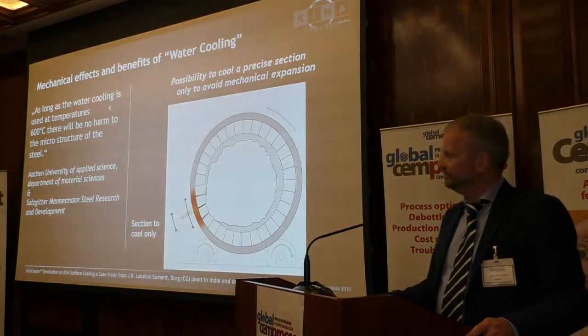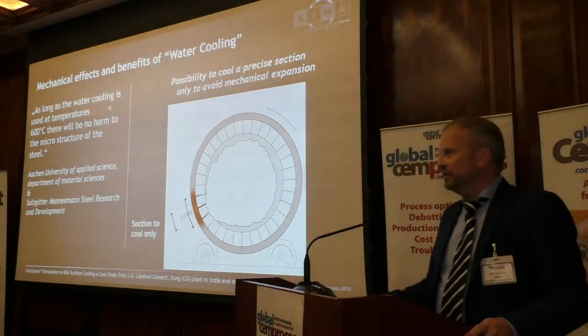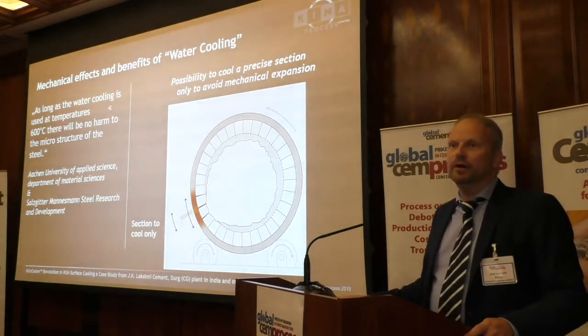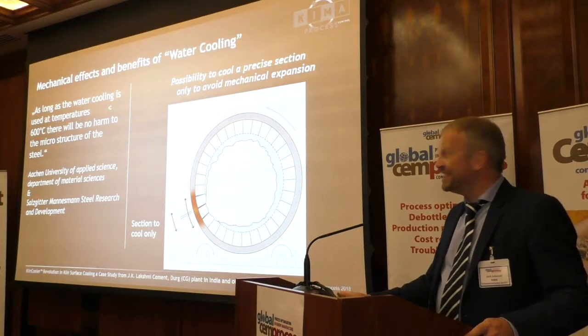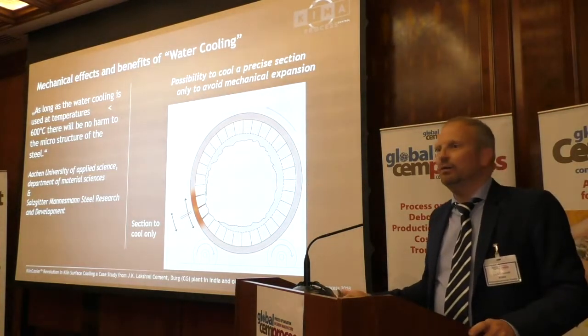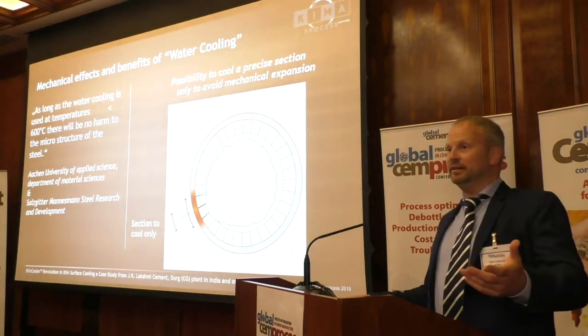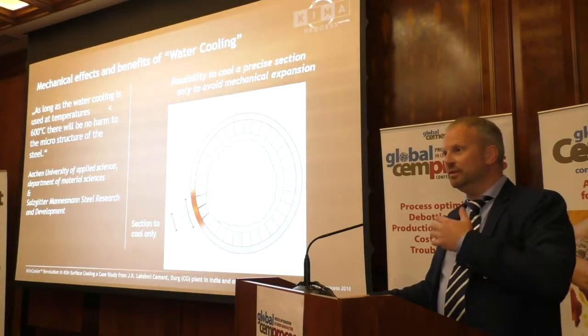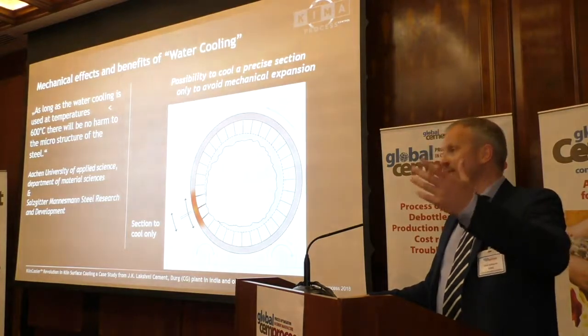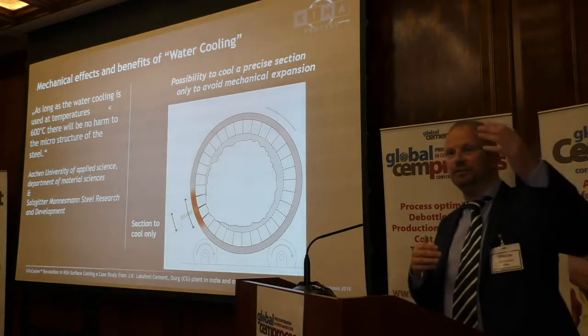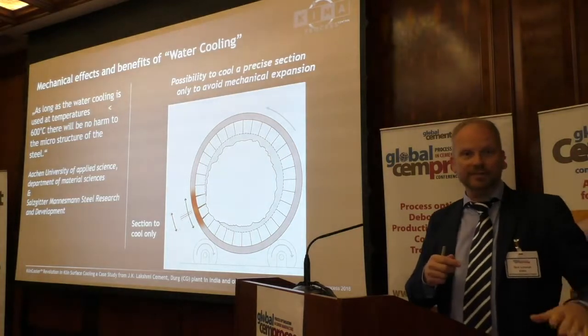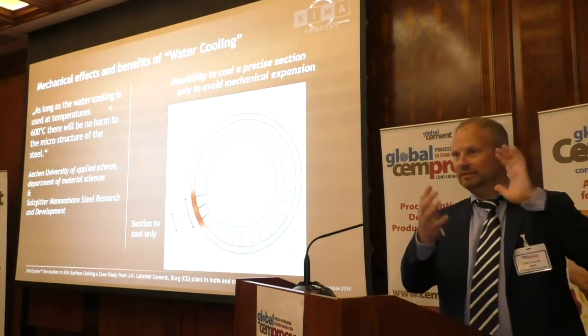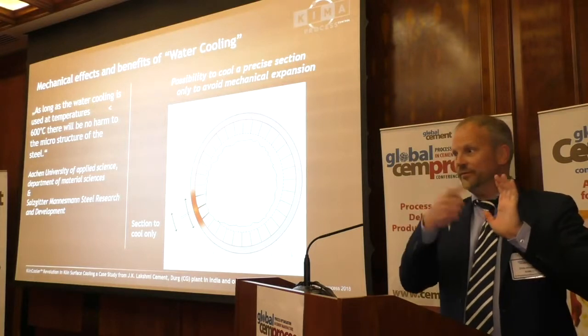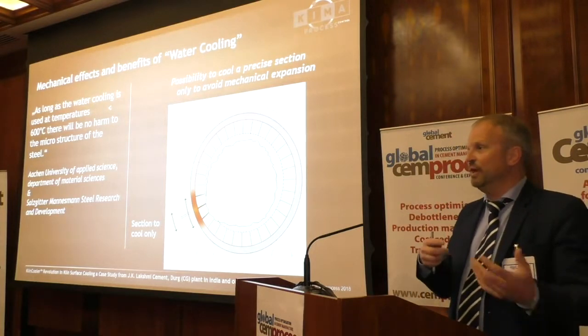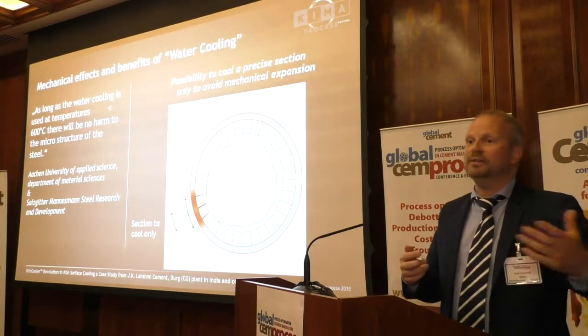Definitely no corrosion. Okay, what is the water consumption per kiln per year? That depends, of course, on the kiln and, as I said here, on the necessity, I would say, how many hotspots they have, how early they start. My recommendation would be not only to start with a system over 300 degrees. Look, if you have a delta T of 40, 50 degrees, even at 270 degrees, it means that you have unstable coating over the circumference. So use it even in this moment to have a more stable coating from the earliest time.